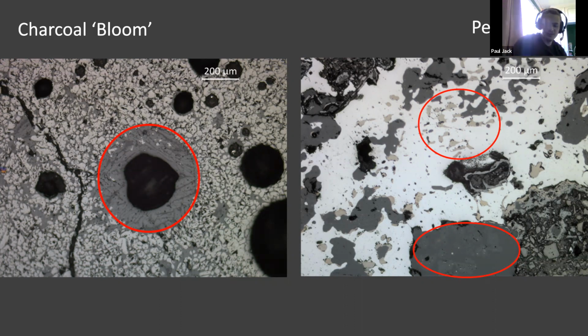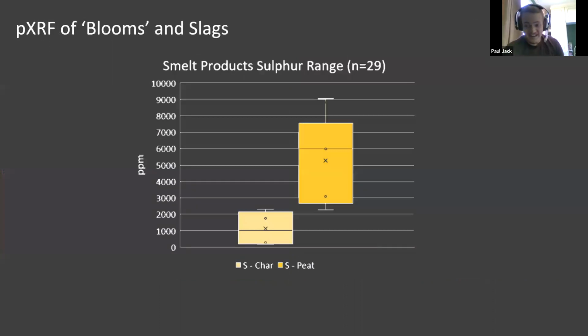And unfortunately, when we did the PXRF analysis, the only difference really between the two sets of material was in sulfur. So this sort of confirmed my worst nightmares that even if we were to fix the blockages and have produced lots of iron, the bloom from the peat fuel smelt would still have been very heavily enriched with sulfur, as we can see here.